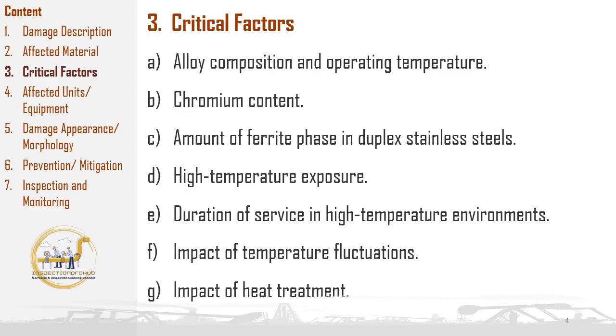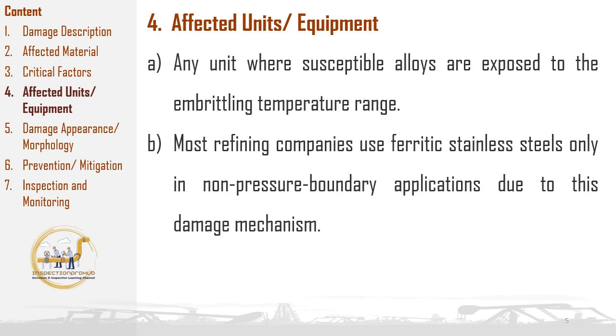This can severely compromise the material's integrity, making it more susceptible to brittle fracture. To avoid this, heat treatment processes must be carefully controlled, ensuring that materials are rapidly cooled or quickly moved through the embrittlement range to maintain their mechanical properties and performance. Up next, in this section 4, we'll delve into units and equipment affected by 885 degrees Fahrenheit embrittlement.